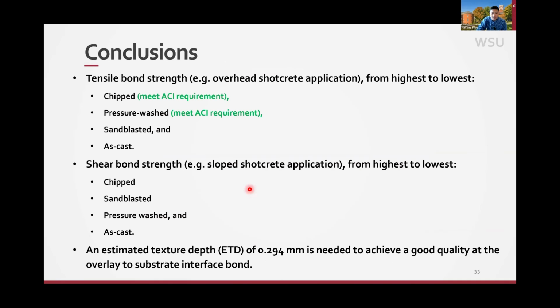Basically, the bottom line from this study, where we looked at the shotcrete and concrete bond, is that for tensile strength there are different scenarios. Sometimes you apply the shotcrete overhead, like in a tunnel, and in those places tension is very important because the shotcrete can fall down from the substrate. In that case, we see that the surface preparations, chipping and pressure washing, can meet the standard.